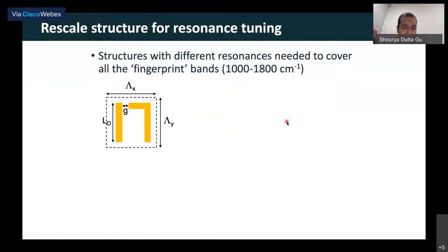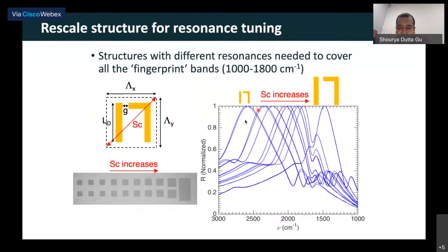So the simple way of tuning is that you take this unit cell, which has a period of lambda x and lambda y, and then you scale it so that you increase the size of all the dimensions that you have. Now by scaling, if I go from a smaller size to a larger size, my resonance will move from around 2500 centimeter inverse to around 1500 centimeter inverse, right? And this is a typical optical image of the samples that we are fabricating. These are the smallest arrays and these are the largest ones, right? So if I put different structures, I'll get different enhancement for different bands.